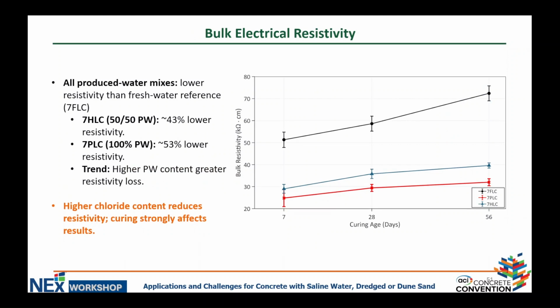Here we can see the bulk electrical resistivity results. Again, as I said, it's kind of hard to say that this test is reliable in the case of produced water or even seawater, because chloride is present in a huge amount in these types of water. Therefore, it does not really show you the refinement of the microstructure. The only application for electrical resistivity in the case of seawater or produced water that is helpful is comparing different mixes made with seawater or produced water and seeing how the electrical resistivity differs between them, but not really comparing a freshwater reference mix and a produced water mix.